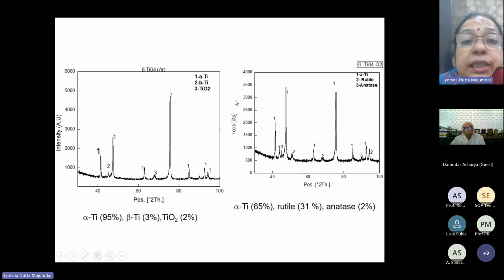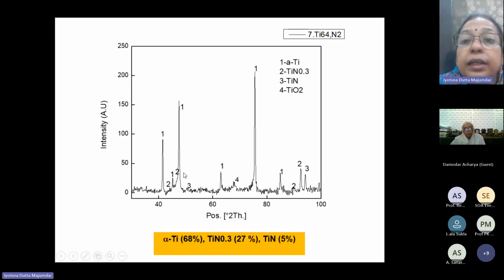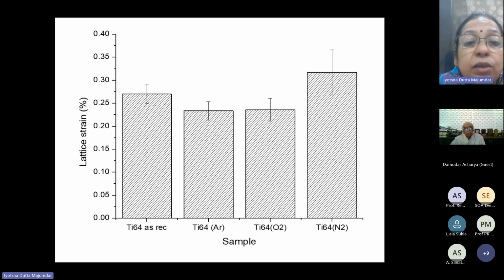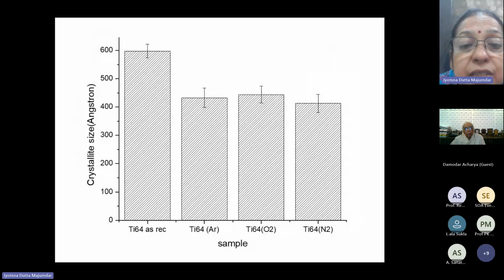So when we did XRD analysis, we found that in the argon and oxygen containing environment there are a lot of oxides on the surface. In nitrogen containing environment there are again nitrides. These are all typical analysis research results.